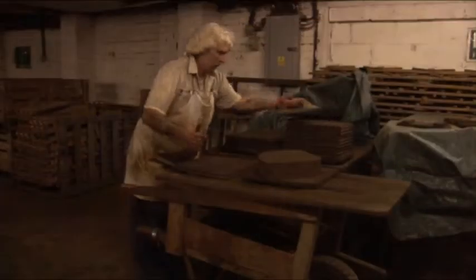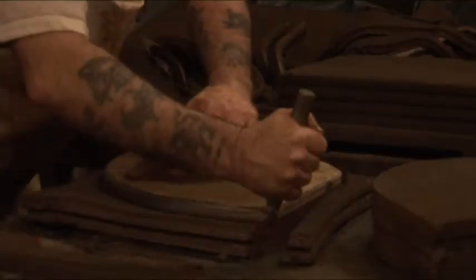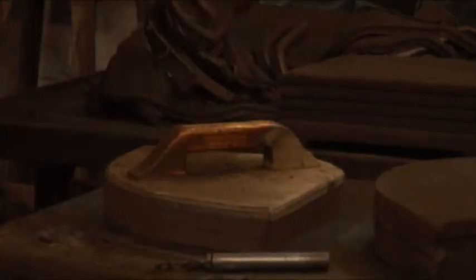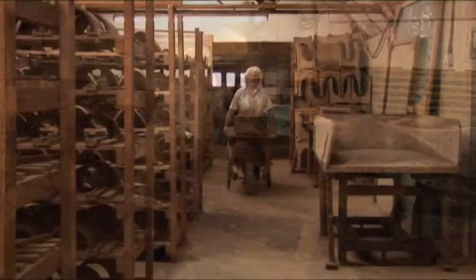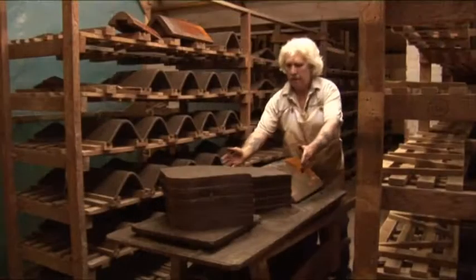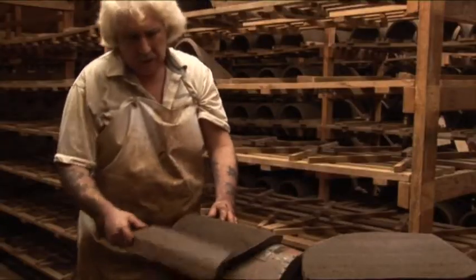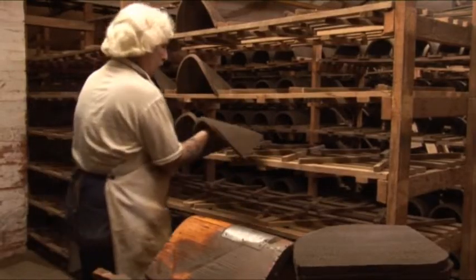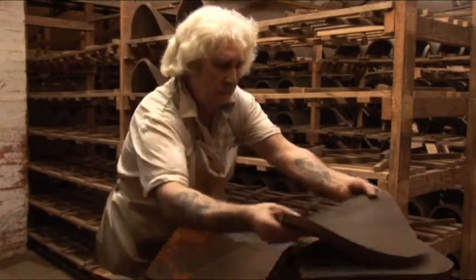The fittings and specials are made by using profiles to cut the clay to the required shape. The piece is then placed over a former to give it its shape. The tiles are then left to dry for around seven to ten days, during which they shrink by five percent.